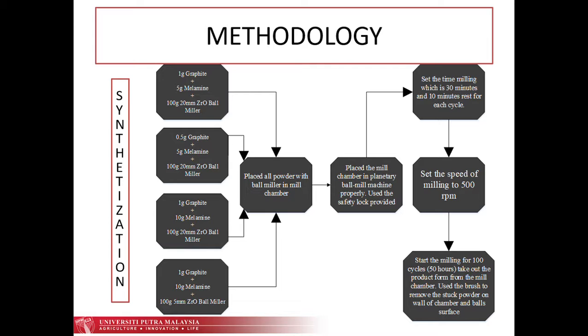Then we set the time of milling for each cycle, which is 30 minutes of milling and 10-minute rest. We set the speed of the milling to 500 rotations per minute, and we start the milling for 100 cycles, which means we are milling each sample for 50 hours. Once the 50 hours are completed, take out the product from the mill chamber and use the brush to remove the stuck powder on the wall of the chamber and also on the ball surface.